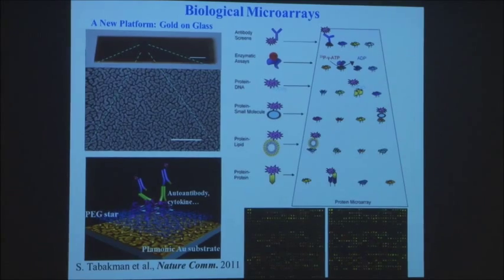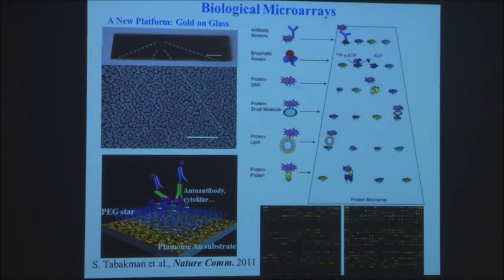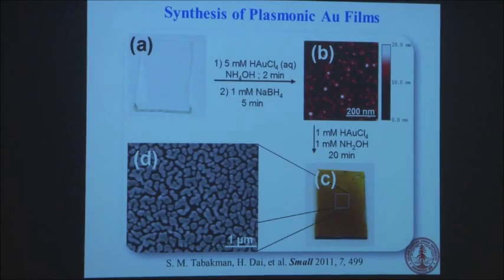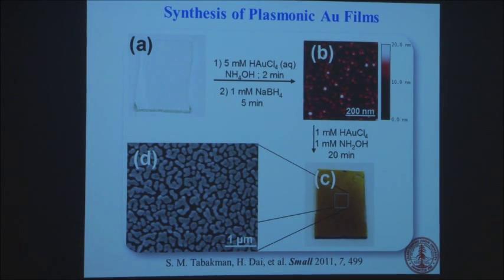So we recently found a very simple way to very efficiently enhance this sensitivity. The way we do that is to use these gold films that are made on glass. These are very small islands of gold that are grown on a piece of glass. We found that this is a very good substrate for making these arrays. And the reason is because of plasmonic enhancement of fluorescence. In other words, these metal structures are plasmonic, which means collective oscillations of electrons in the metal structure, and they can couple to the fluorophore and enhance fluorescence.